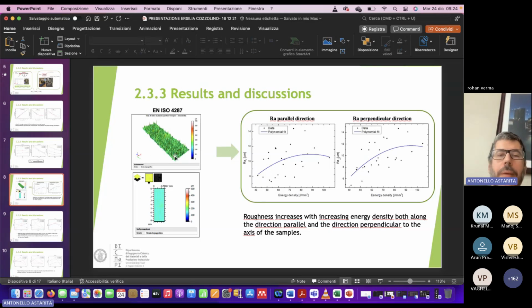We used a three-dimensional scanner to have the 3D representation of the surface and to calculate, according to the standard, the surface parameters for roughness, because usually what you do is to calculate the linear parameters for roughness, but in 3D printing, the linear parameters are not detailed enough to catch the actual shape, the actual geometry of your surface. So the parameters that are more useful to capture the surface are the surface parameters.